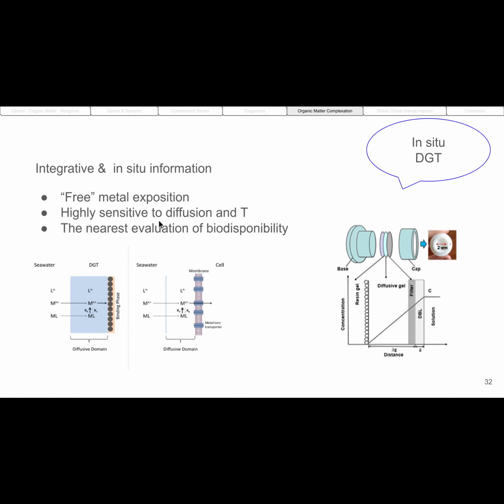It's a highly sensitive technique, but it's also sensitive to temperature and diffusion. So you need to measure in situ at the same time the temperature and the diffusion and make some calculations to extrapolate the concentration of metal that was seen by the DGT. Also, in sediments from mangroves, it's perhaps not the most appropriate technique, because you need a long exposure time, generally around 1 week, and it's not able to take into account all the changes that can occur during a tidal variation. So you have something averaged or integrated, but it's difficult to deduce what can happen inside the sediment.